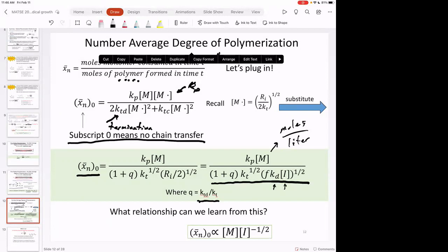Just Mn over M0. That's right. It's Mn over M0. And I tell you what the polymer is, right? As soon as I say polystyrene, or polyethylene, or polyvinyl chloride, you're like, boom, I've got M0. I either need to know the degree of polymerization or the molecular weight, and I can get the missing variable. So the key is that you need to solve this equation for the concentration of I, because you know everything else. And so it should be easy, right?